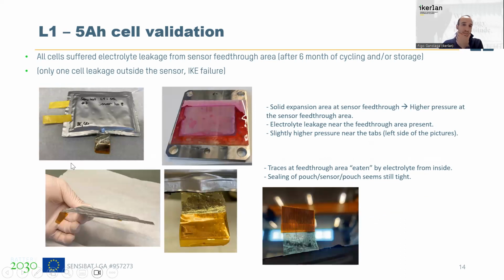But we had some problems with those sensors. As you can see in those two pictures here, the traces of the sensor, so in the feed-through area, were eaten and they were completely erased in some parts. So at the beginning, we were able to measure the pressure and the temperature from the sensor, but at a certain point, the electrolyte gets inside the sensor and it is corrosive.